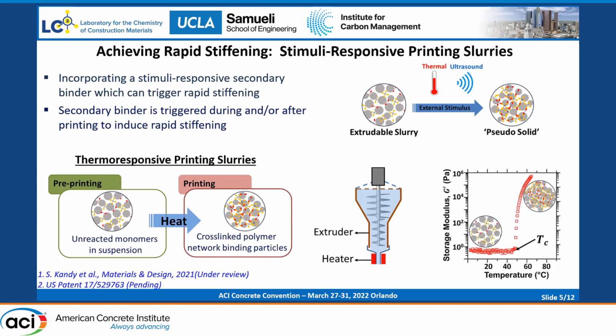So what happens is these suspensions remain flowable until it reaches the activation temperature. There won't be any significant change in the elastic modulus. But once it is heated above the activation temperature, the polymerization starts and the polymer network builds up within the suspension matrix. And as the cross-linking proceeds, this rigid polymer network forms around the mineral particles that induces this rapid fluid to solid transition.